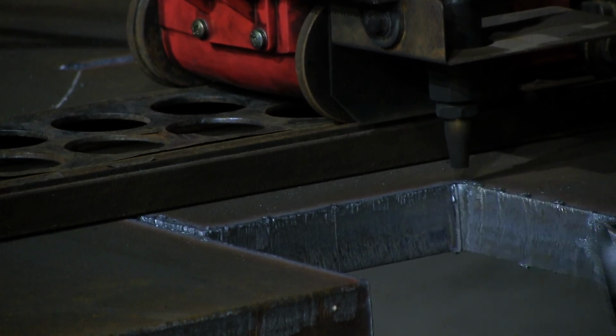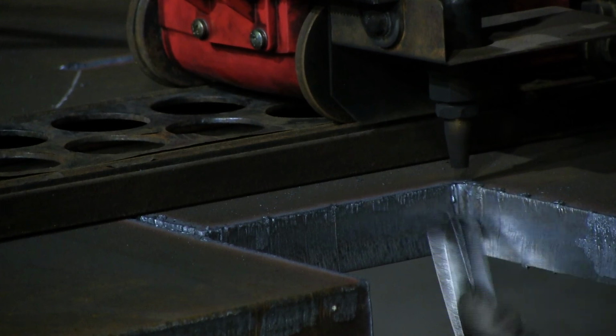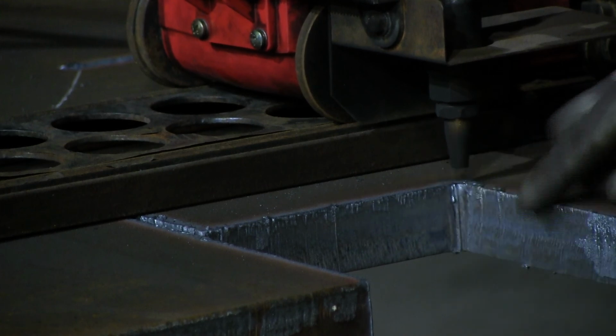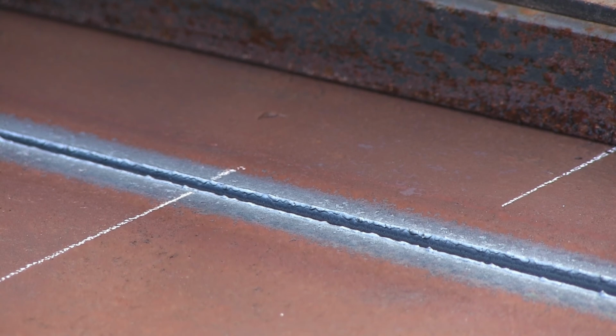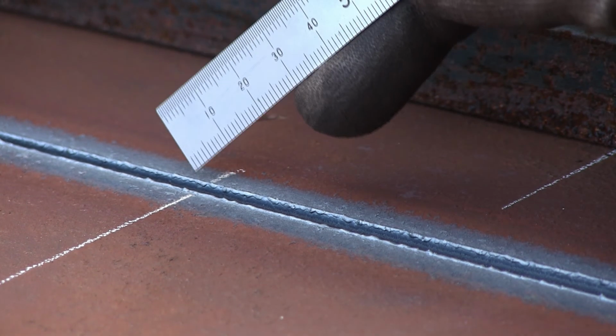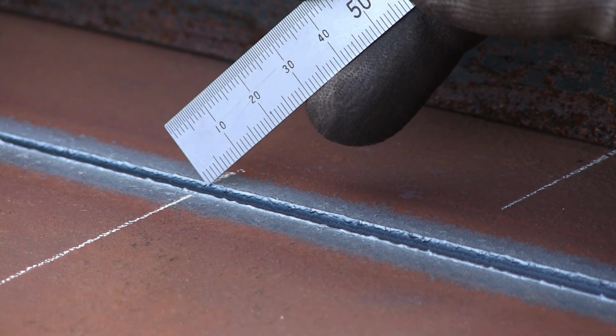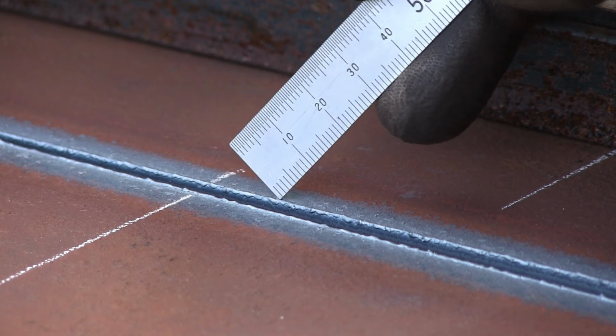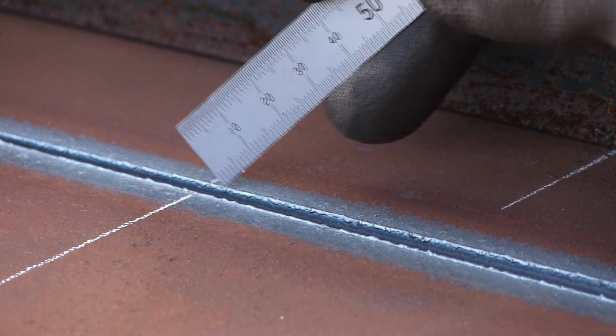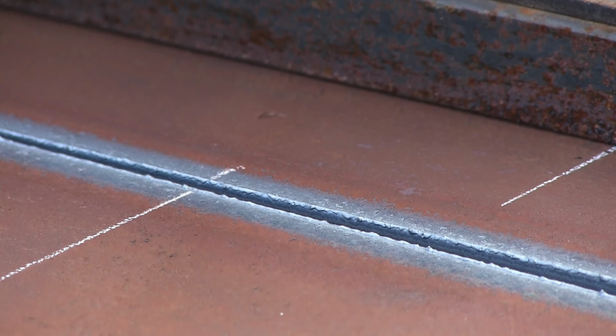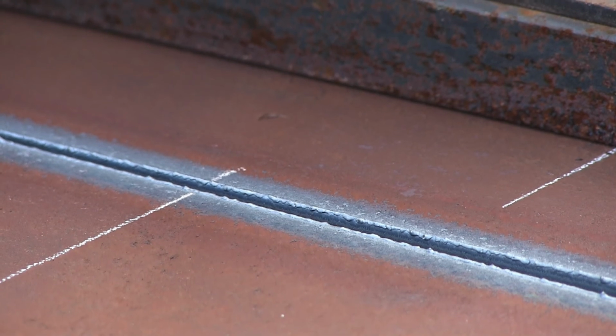Some applications may require you to have a very clean and sharp edge of a cut, and that can become quite more difficult, because to achieve the top edge sharp, that means that your heat needs to be hot enough to burn well, and cool enough not to melt the edge. And it comes with experience, and if you don't really do much, it's very easy to muck it up.